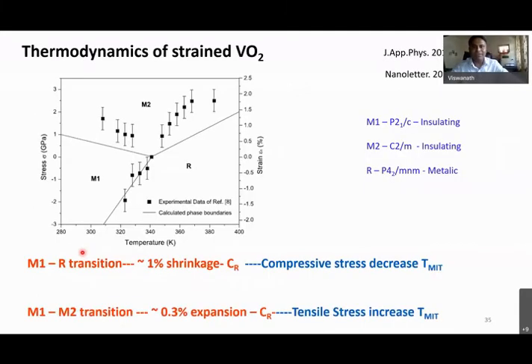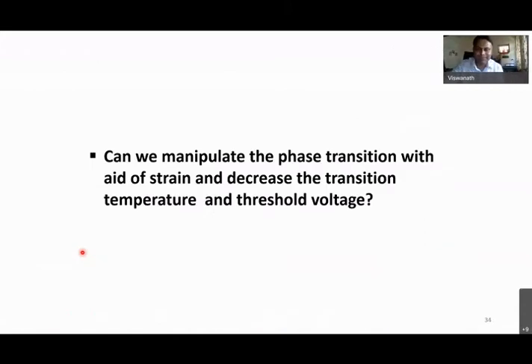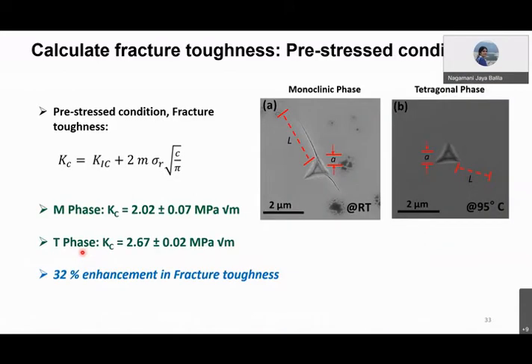I'm not very sure we have time. I can ask one more question, Viswanath, right here. You could also add the phase transformation stress to this, right? For T phase, possibly the fracture toughness is even higher. You had about 300 MPa tensile stress.